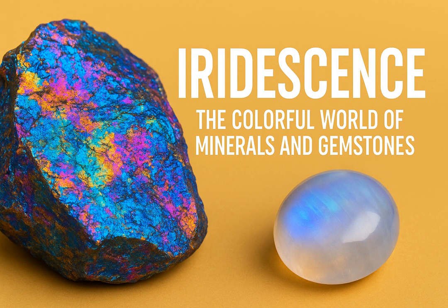that dazzling way. What's truly remarkable is that despite being optically distinct, the orthoclase and the albite-oligoclase structures are crystallographically coherent. Coherent? Meaning their crystal axes are coincident, or nearly so. They line up, allowing them to grow together seamlessly at a microscopic level, even though they're slightly different. Wow, that's complex. It gets even more remarkable when you consider twinning.